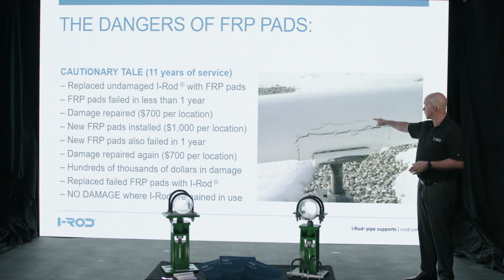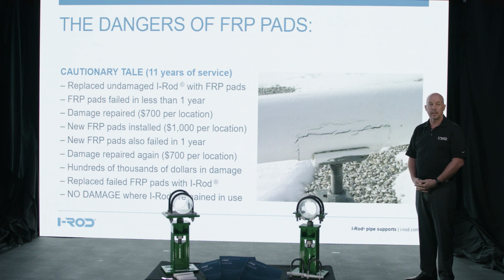And you can see here this image, the line that's at the top of the wear pad is the first FRP pad that was removed, the damage from the first one. And this, a year later, is the second one that's shown here, this dark area around the FRP pad. So it only took another year, failed the same as the other one. That's when this operator contacted me and asked me why the pipe supports where I-rod was still installed on the flat, there was no damage. 11 years later, pipe still looks great at those locations. However, where these FRP pads were installed, it's already failed twice in 2 years.